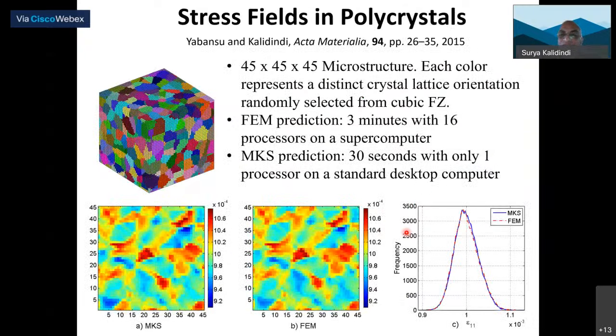Everything I showed there is about homogenized properties. It turns out that another variant of this can actually predict the local fields. So now we're not just interested in the effective properties of the microstructure, but we want to see the strain field or stress field, voxel by voxel. This is ground truth from finite element. This is what is predicted by our knowledge system. And you can see that pixel to pixel, we are making incredibly accurate predictions.